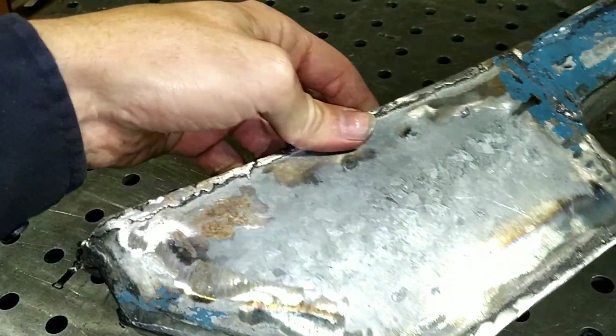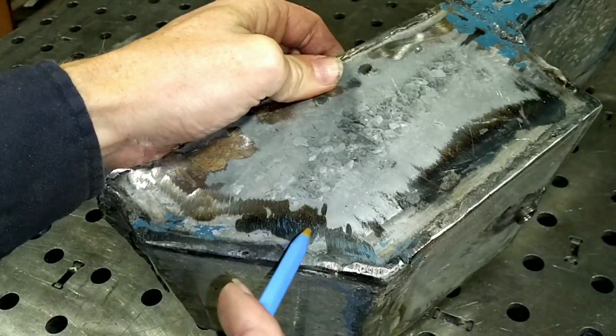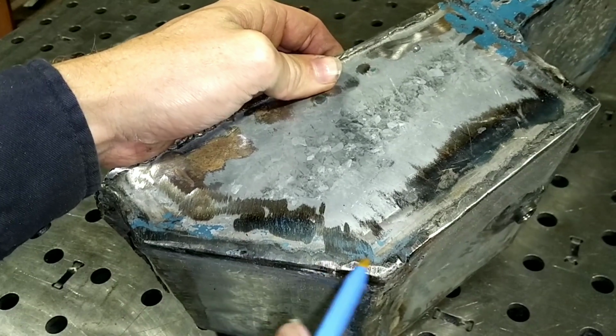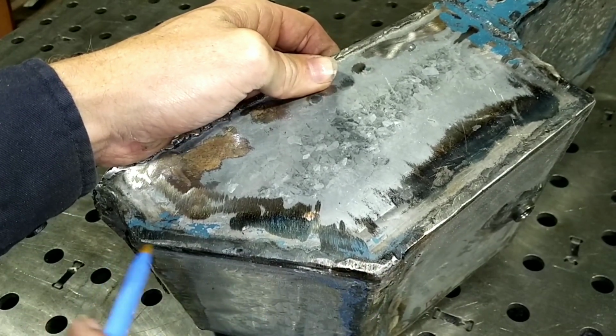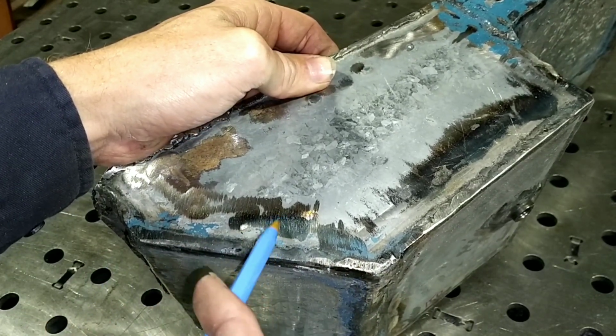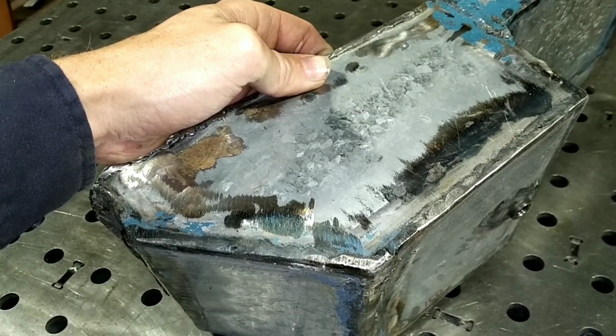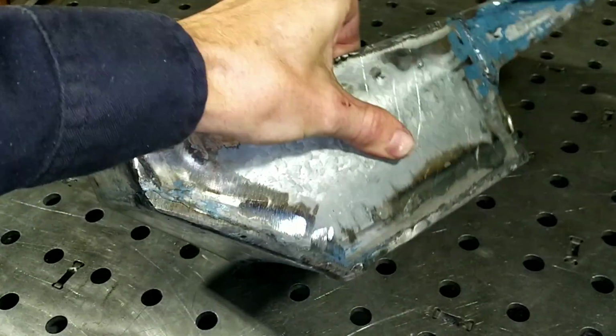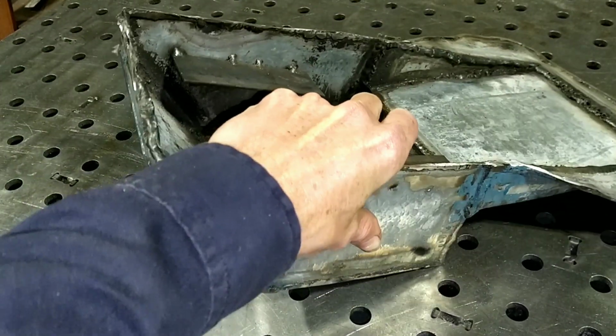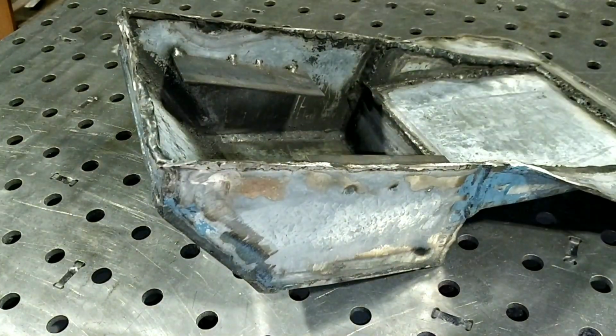You can see along here where they've started to clean the gal off just to get a slightly better weld. One of the better welds of the actual job here is because they removed the gal. You can't weld through the gal. The reason is zinc atomizes at a lower temperature than steel will take to fusion. So you'll have literally gas pouring out from the surface, being zinc, that will then want to push into your weld, and that's where you get all the porosity and all the holes.